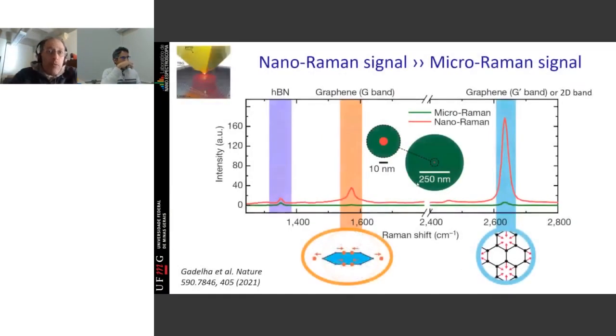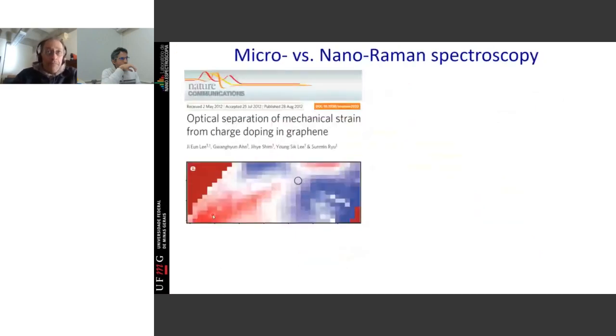And the important result, which is shown here, is that the green spectrum that you see is the spectrum that you obtain in a large area of the spot when you have the laser focalized with a microscope objective. Then if you land the tip, the signal enhances very strongly, but this very strong signal comes from a very small area, which is 10 nanometers inside, the apex of this antenna. And now if I scan the antenna all over, I can make images of the system, okay? And let's give examples of what we do with this.